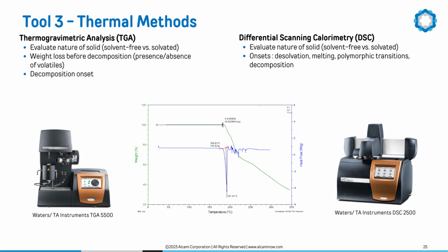Following are thermal methods, namely thermogravimetric analysis and differential scanning calorimetry. They are different but very complementary techniques. They assess thermal behavior of API upon heating. TGA measures weight loss before thermal decomposition that can be due to a hydrate or a solvate, and during thermal decomposition. DSC measures onsets or heats of transitions of key events such as melting, desolvation, polymorphic changes, and decomposition.